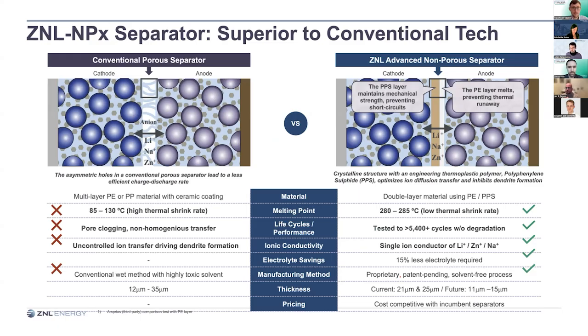We also have a PE layer on the anode side. If you have a thermal event, that will shrink, but the integrity of the separator will hold because of the high melting point and the low shrinkage that we have on the PPS. You don't expose the electrodes. What happens in a conventional separator when there's a temperature event is that it will melt and you expose the electrodes.